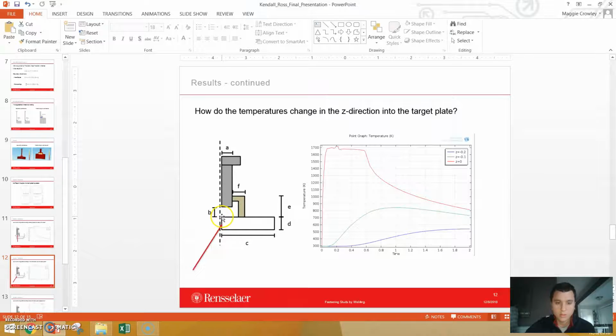One is the corner at Z equals 0, which is the corner of the target plate. And then I went down and made 2 points that are 0.1 and 0.2 inches into the target plate. And you can see that the further you go down into the plate, the lower the temperatures you see, but you're still getting some really hot steel here. So even almost a 1/4 inch into the plate, you're looking at 500 degrees Kelvin. So it's pretty hot. And just 0.1 inches from the top of the plate, you're at 800 Kelvin.